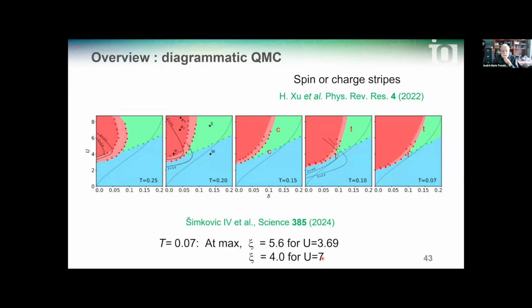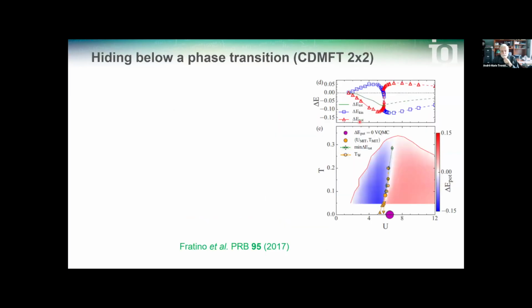Here I want to say that even if there's no phase transition in the ground state delimited by the solid line, there can still be different, although adiabatically connected, physics associated with interaction strength not large enough to lead to an insulator at that filling and those large enough. Let me illustrate this concept of being in the same phase, yet of feeling whether interactions are strong or weak. This is a plot at that filling, CDMFT, so temperature as a function of interaction strength.